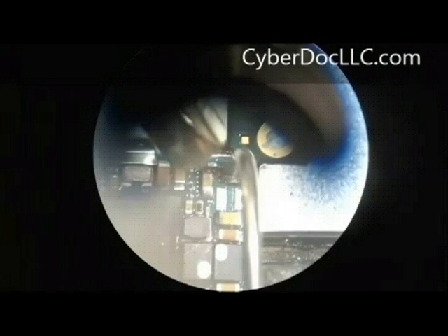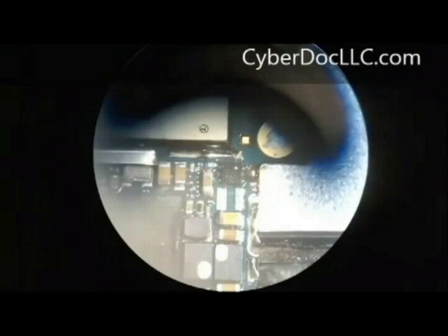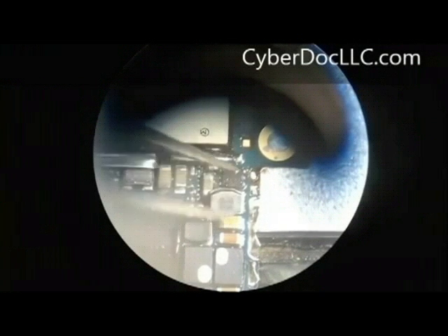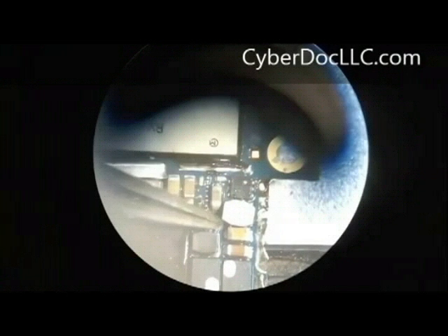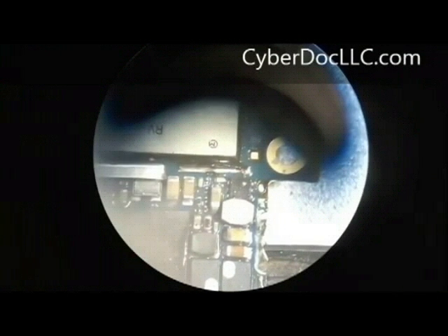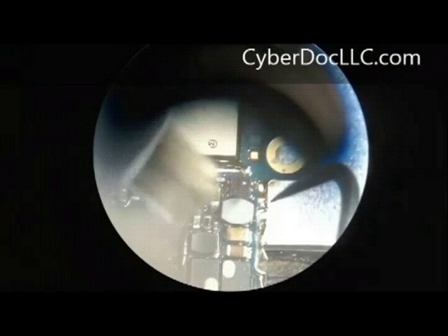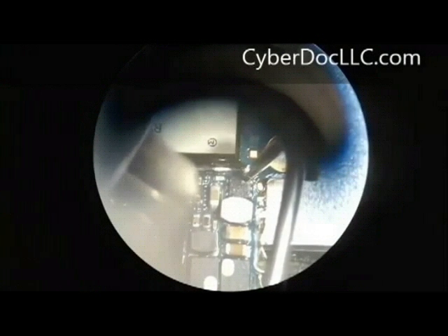I'm poking with my dental pick right now, because even if you heat the alloy, it's not a guarantee that the alloy will take hold onto the metal parts on the IC. It's not a guarantee it will take hold, because you also have to heat up that metal part in order to get the capillary effect bonding from the alloy to the metal joint, the IC's metal legs. And using a dental pick poking at it, you create necessary stress and force or vibration, give or take, to get those alloy to mix with the joint on the IC. And also you press it down, so you get a bit larger surface area to get the bond happening. And now I'm just poking the IC too.